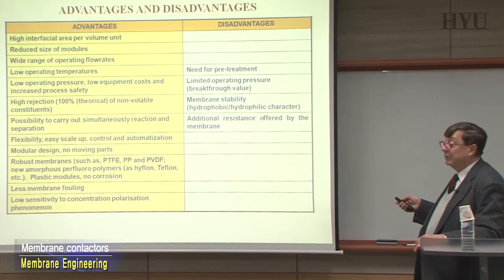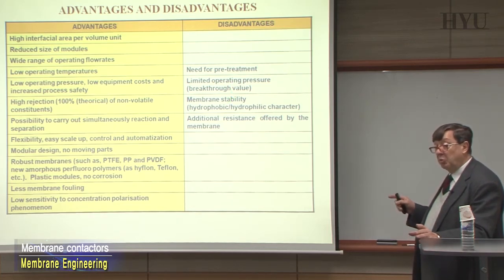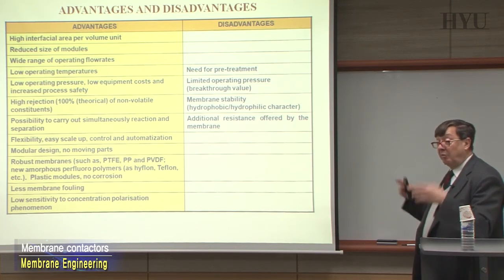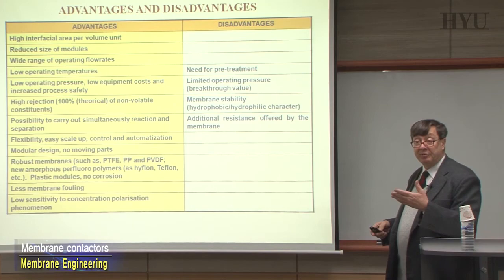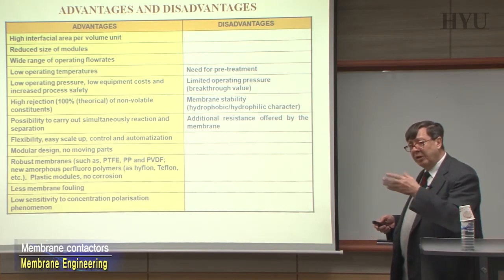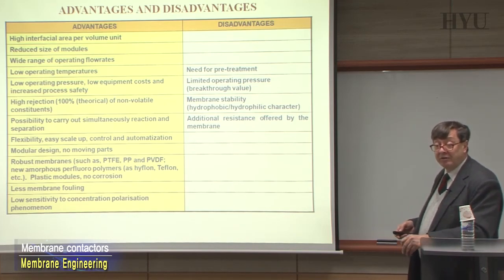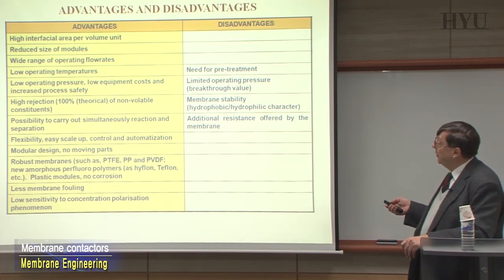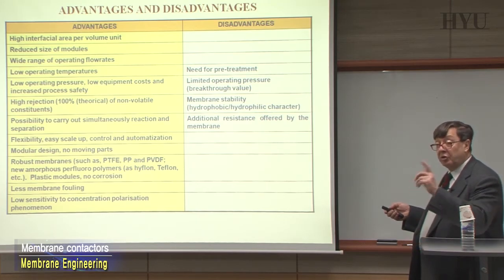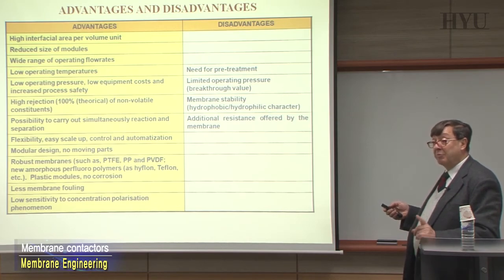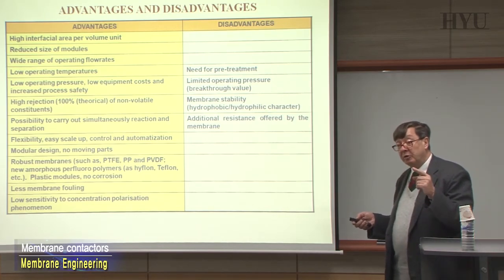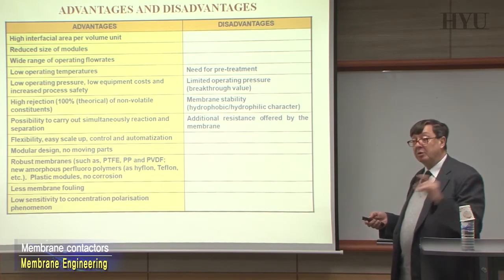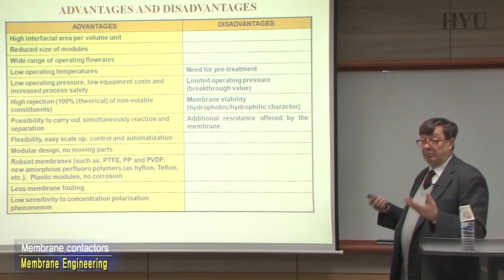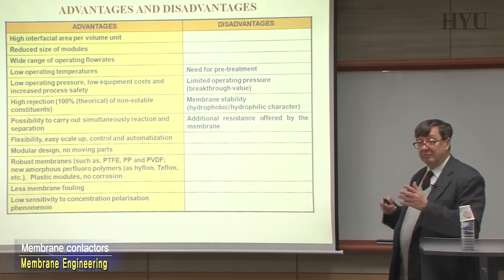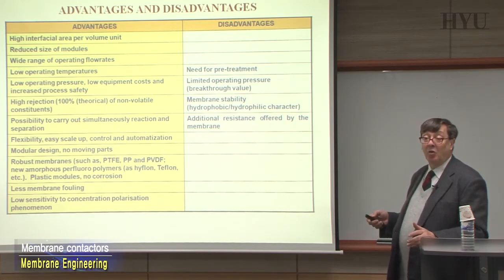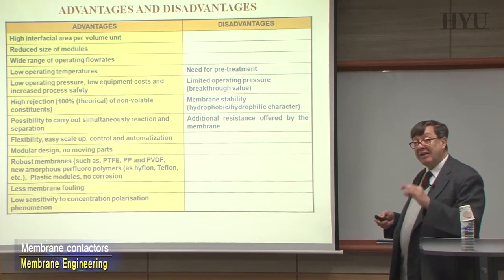We have to be careful about the pressure that you apply on the system. We don't need really pressure, but in a complicated system, in a big module, you can have pressure drops across the system when you have your water flowing on the membrane surface with your cross-flow system. This is a problem that you have to keep under control, because if you are increasing too much the pressure drop, you are pushing liquid water across the membrane, across the porous system. The hydrophobic character is valid, it has to respect some law. That means it's related to the surface energy, to the size of the pore, etc.